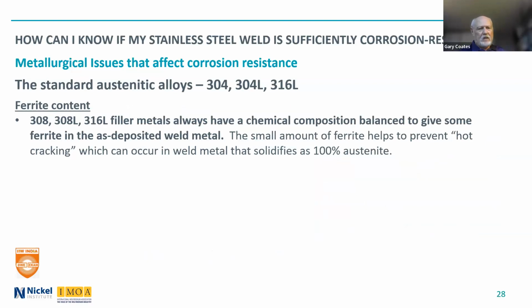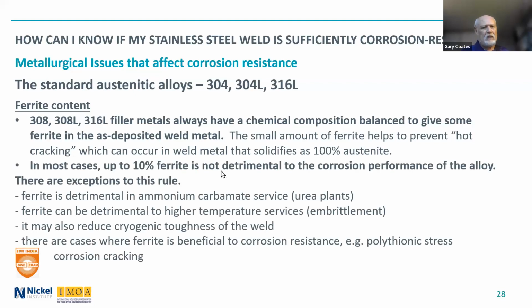What about ferrite content? Well, as mentioned, those alloys, 308L, 316L, the composition of the filler metal is balanced to give some ferrite in the as deposited weld metal, and a small amount of ferrite prevents hot cracking, which can occur when that weld metal solidifies as 100% austenite. And in most cases, up to 10, even 12% ferrite is not detrimental to the corrosion performance of the alloy. But like all things in life, there are exceptions.